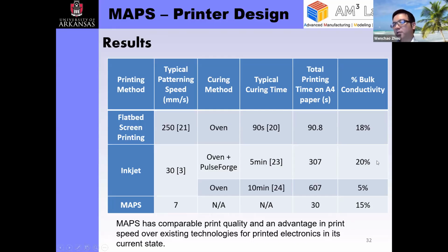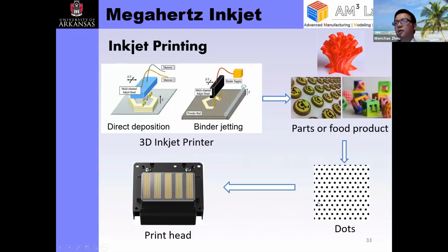One of the things to realize is that this MAPS prototype we developed is the first generation, and with some simulations, we can show that we can speed up the printing process by another 10 times with MAPS, with some additional control mechanism, and hopefully even higher quality, which we haven't tested yet. So that is MAPS. And another project we've been working on was inkjet.